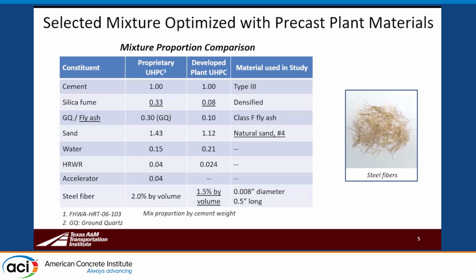Steel fibers, this is something that we looked into. We thought we would at least try to reduce the steel fiber content a little bit to see if we could make that work well in order to reduce the overall cost of the UHPC, because the fibers are a big part of that cost. Based on some of the direct tension testing that we did to compare, we felt we could start with that 1.5% volume. Certainly you can use higher volumes of fibers and enhance the tension performance, but we were trying to meet some minimum requirements and were able to do that. This is a look at the steel fibers. They're very fine, needle-like fibers of a 1/2 inch length.